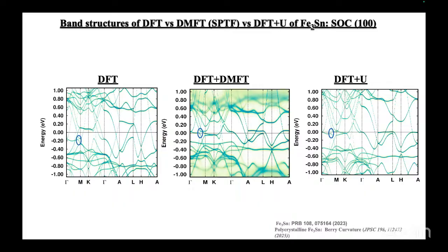So we speculate that the difference in the Hall conductivity reported experimentally for the single crystal and the polycrystal, between the theoretically calculated value and the experimental value, might be due to the unaccounted electron correlation. If we go with DFT plus DMFT or DFT plus U and further investigate the Berry curvature, which has been modified, and the Hall effect, one can overcome the discrepancy that we notice in the literature.